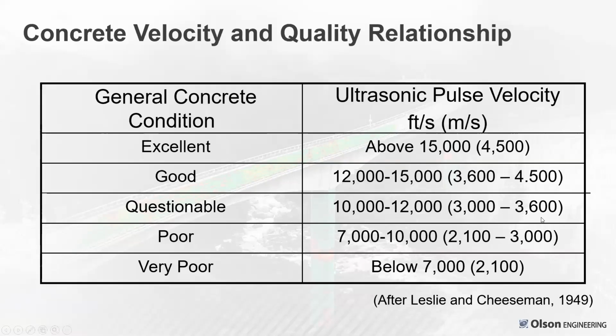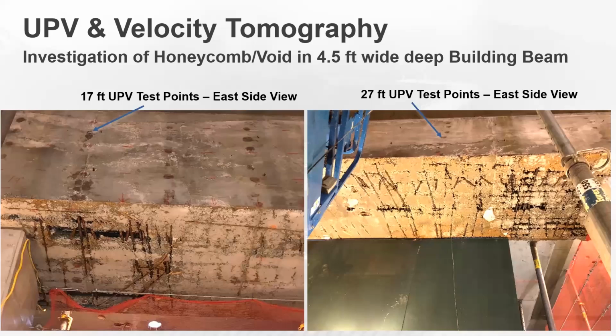Softer aggregates is slower. Stronger concrete is faster. More cured concrete, going say from 3 days to 28 days, just like strength increases with time for fresh concrete, velocity increases with time, till after generally most modern concretes within a couple months have reached most of their velocity for sure.